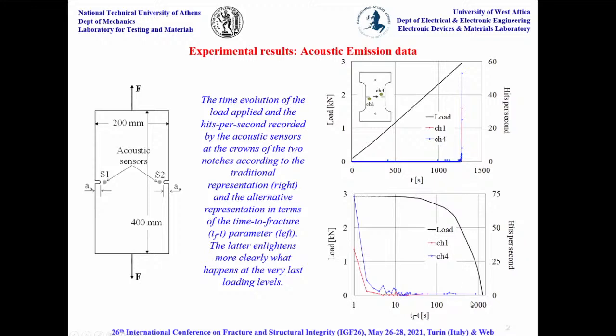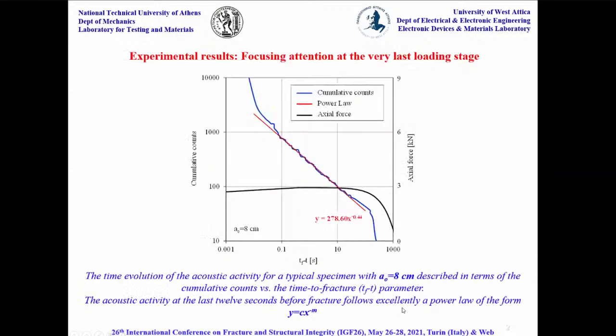So usually we plot the results in an inverse time arrow, the so-called time to failure parameter, and mainly in logarithmic scales. You can see, comparing these two figures, that we have a better insight into what happens during the very last moments before fracture if we plot our data according to this inverse time arrow. Now, we focus attention mainly on the steps just before fracture. From a total duration of about 1,000 seconds, we focus attention on the last 20 or 30 seconds.